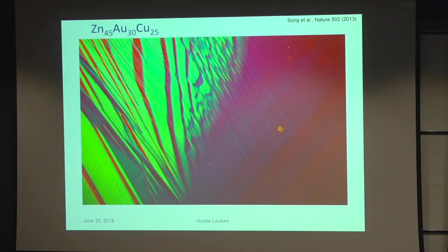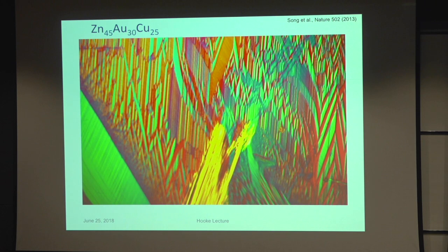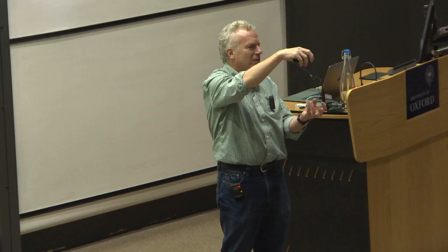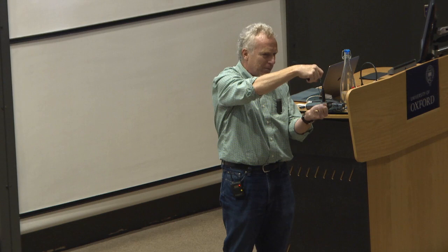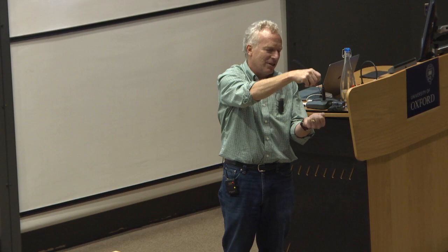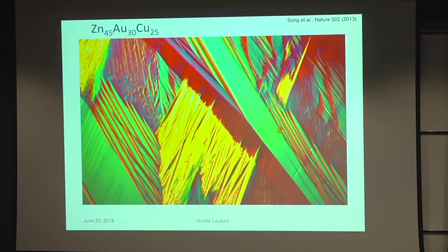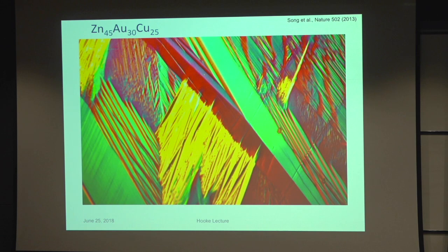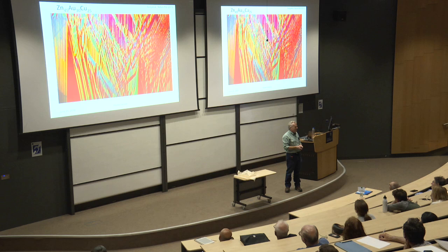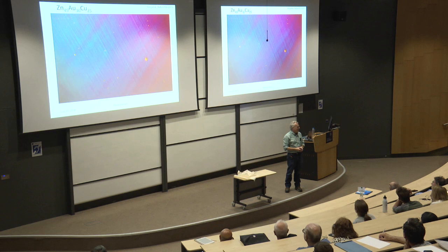To explain it a bit more, in the cubic phase, the boring gray one, you can raise the temperature to some higher temperature and you're always in the gray phase, but you can cause it to transform by putting stress. That's the most demanding test of a phase transformation: doing it under stress. Even though it's zinc, gold, copper, which is never expected to do this, this material can go 100,000 cycles with a stress which would make the steel in this building fail. It's about twice the failure stress of the steel in this building.